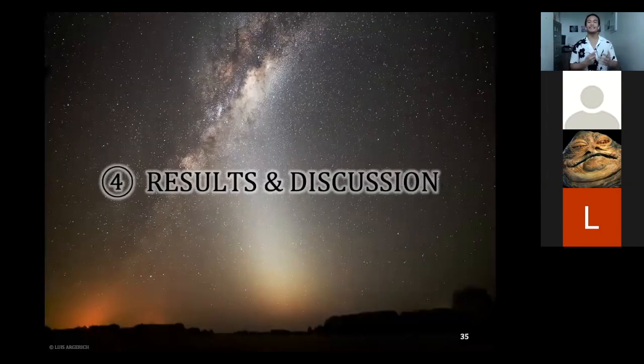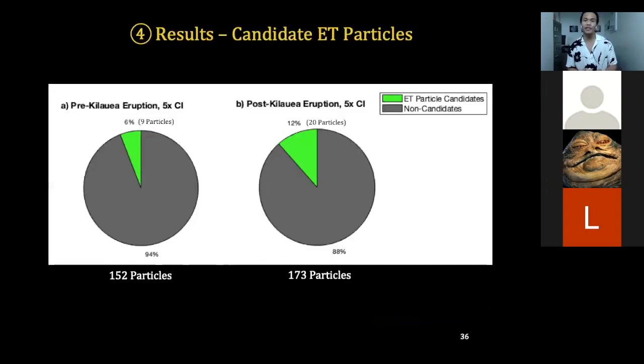Moving on to the results and discussion portion of this talk, starting with the percentages of the extraterrestrial particle candidates in both the pre-Kilauea eruption filter and the post-Kilauea eruption filter. For the pre-Kilauea eruption filter, we were able to analyze 152 particles, of which approximately 6%, or 9 particles, are extraterrestrial particle candidates. For the post-Kilauea eruption filter, we analyzed 173 particles and determined that approximately 12% of those, or approximately 20 particles, are candidates. We also did these measurements using stricter factors of 4 times and 3 times the CI chondrite composition, just to see the numbers. I'll show you that on the next slide.